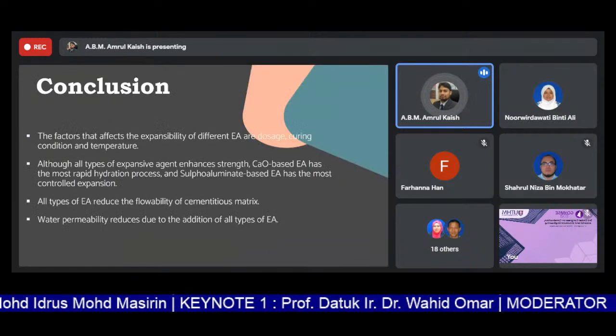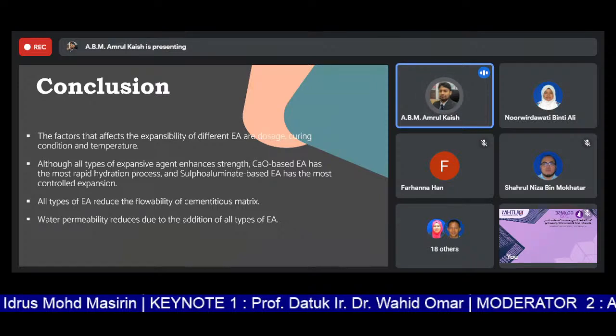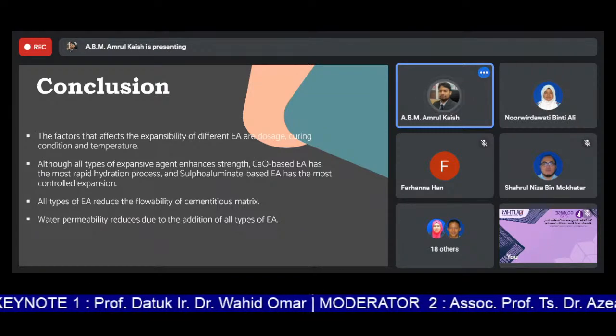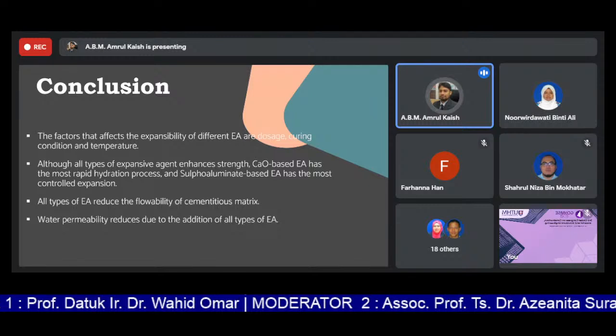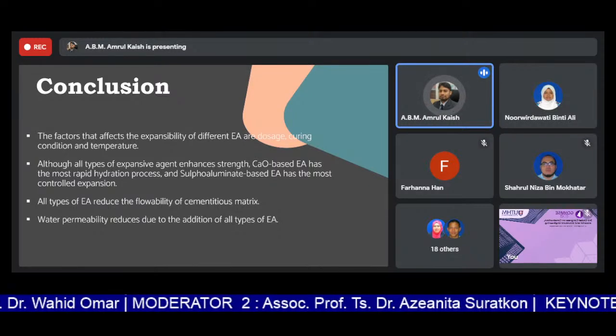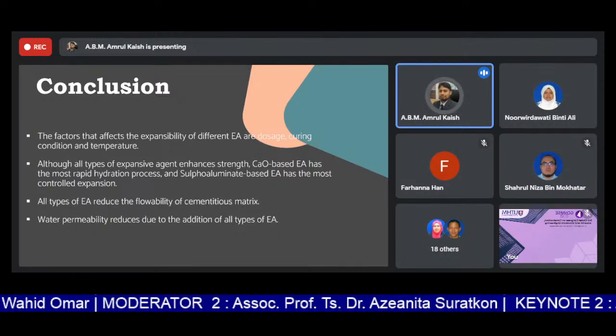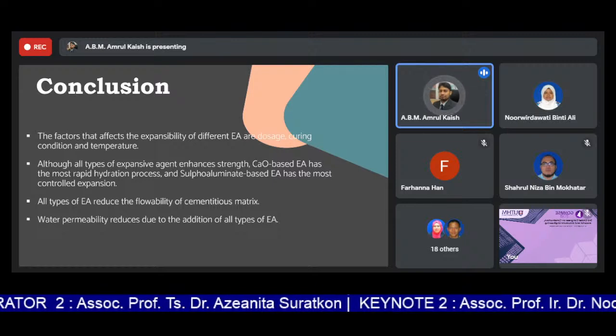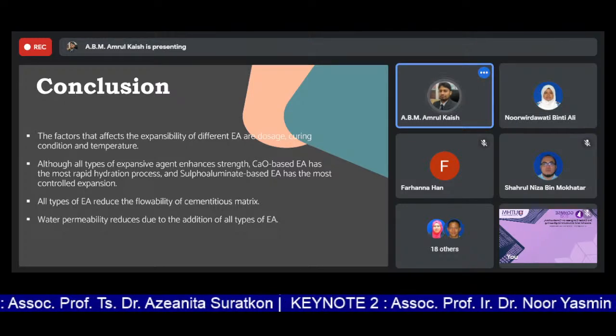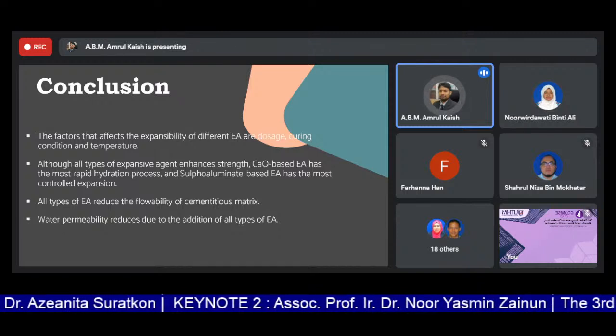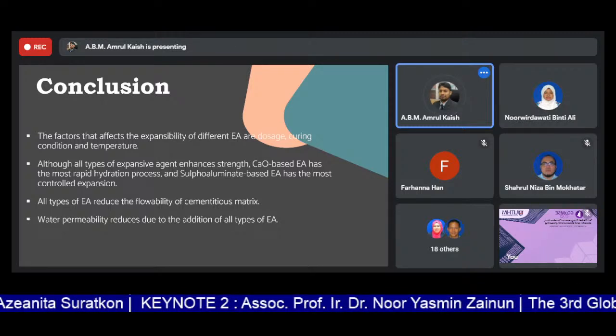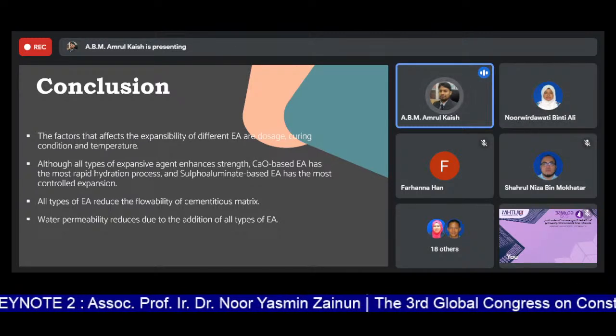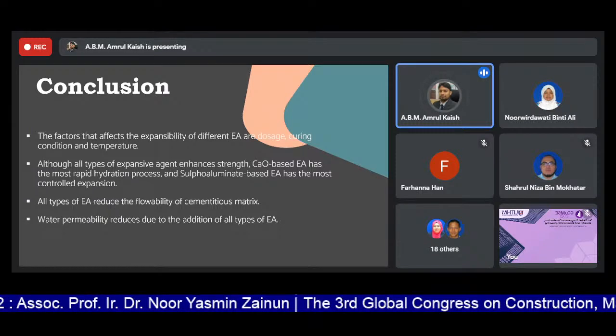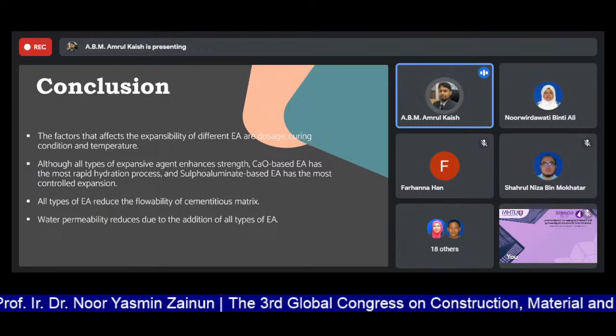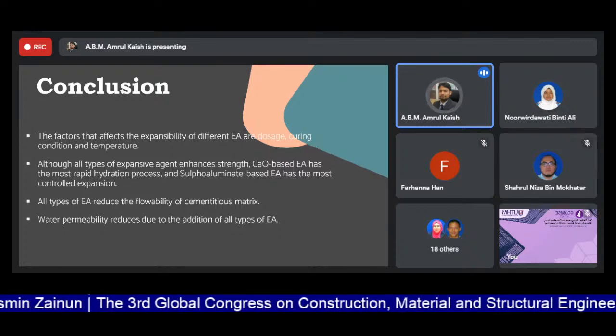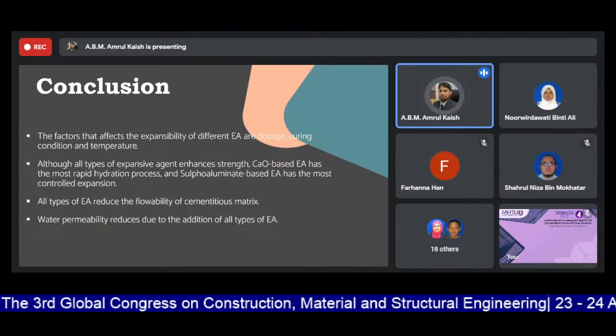In conclusion, the factors that affect the expansibility of the different expansive agents are doses, curing condition, and temperature. Although all types of expansive agent enhance the strength, calcium oxide based EA has the most rapid hydration process, and sulfoaluminate based EA has the most controlled expansion. So for the high early strength, we can recommend calcium oxide based EA. However, for the controlled expansion, which is required for practical use in structures, we should go for sulfoaluminate based EA.